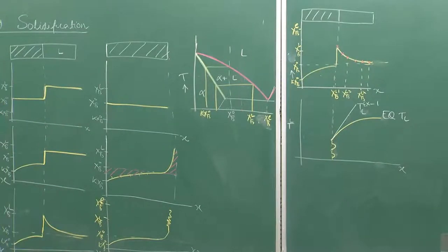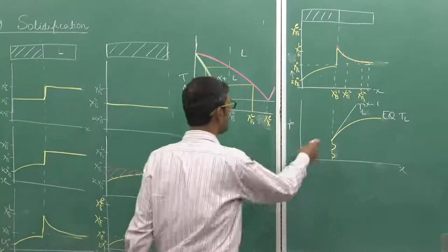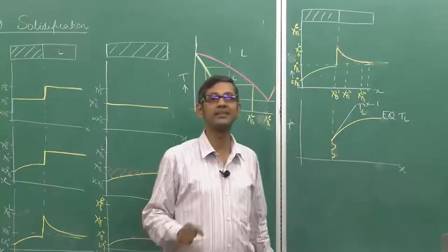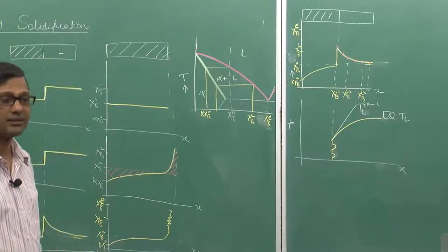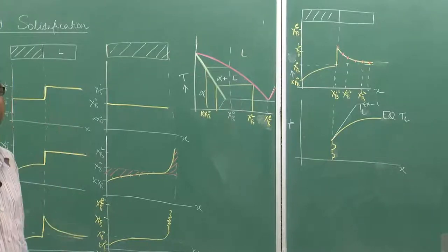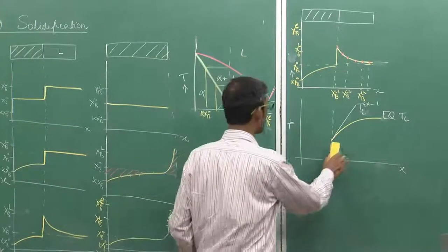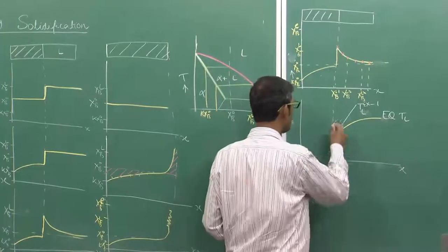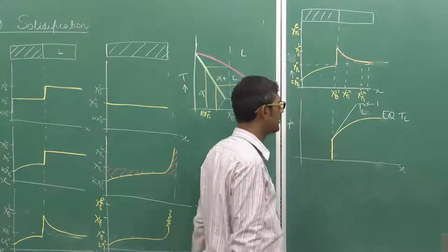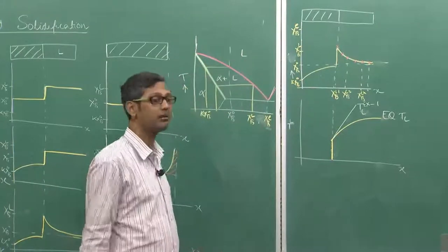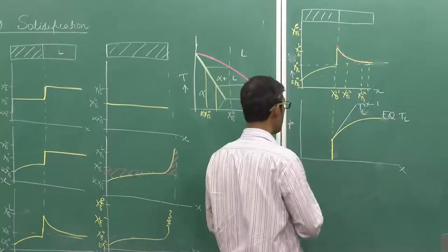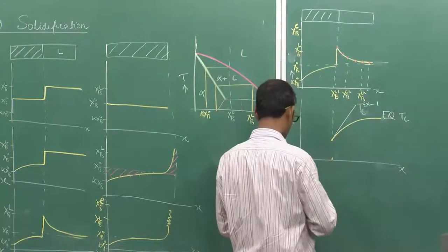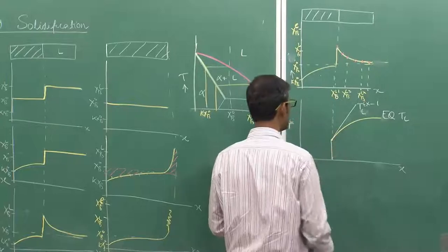And because of that, if there is at all any kind of protrusion or anything that forms in the interface, if the interface becomes a little bit jagged, just like the ones I showed you in the last lecture, they will melt back, and the interface will remain flat. So this is experimental condition 1, in which the interface will remain flat. It will not form any kind of features. Let me draw this as a white line so that you do not forget. This is my first condition.